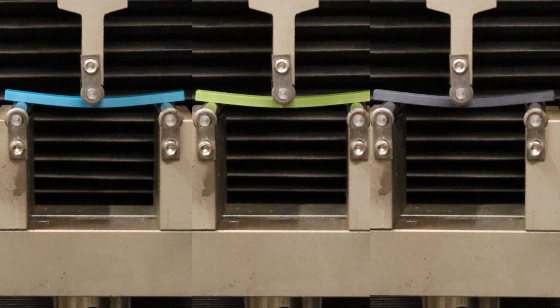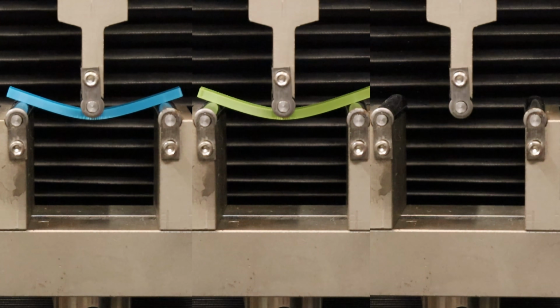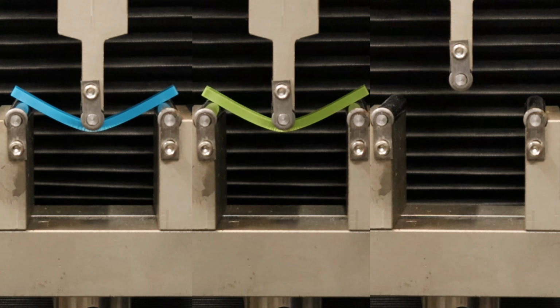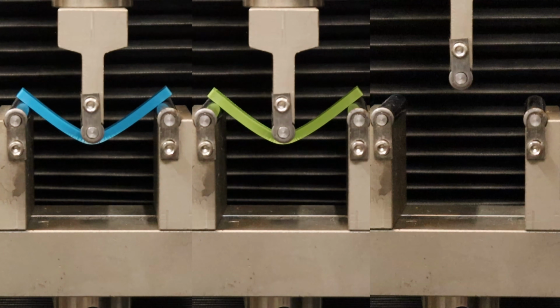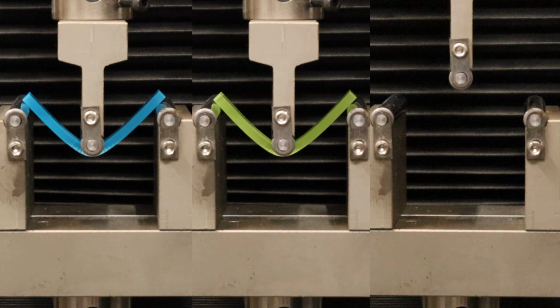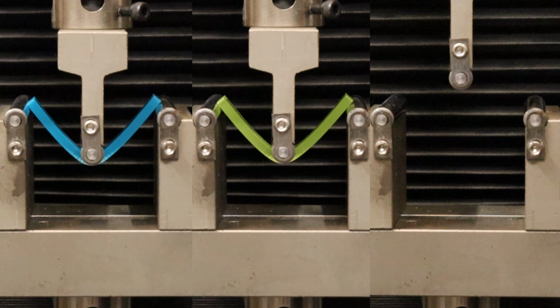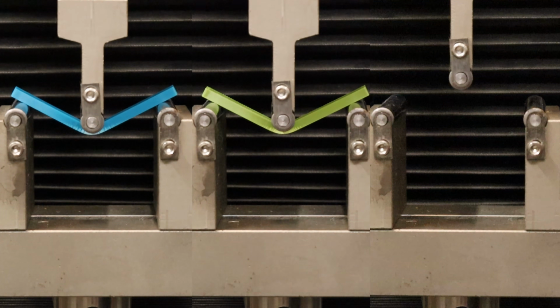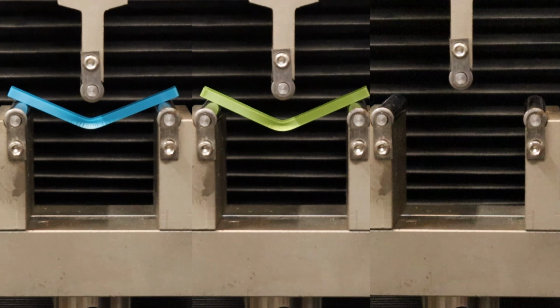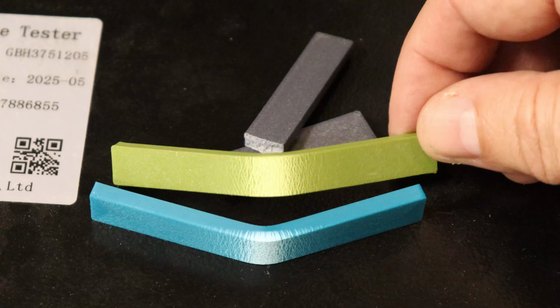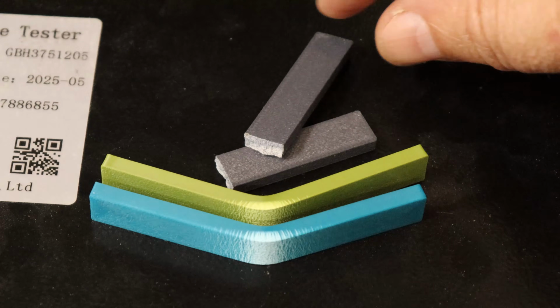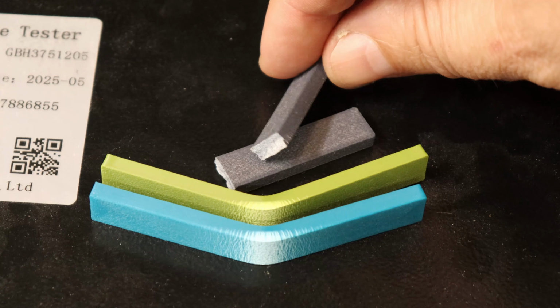Another bending test, speed up 4 times. The ASA-CF broke very quickly. I'm following the ISO 178 standard. Distance between supports is 64 mm. Interesting to see this whitening of the surface, very useful, sign of the higher stress.